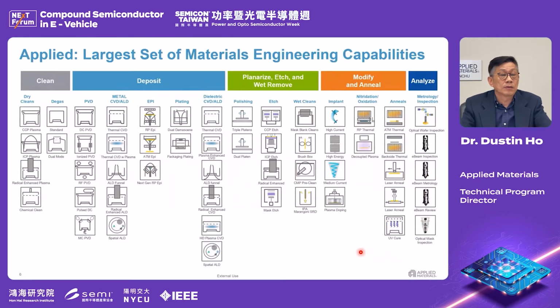Applied Materials offers a lot of equipment for our industry. To simplify, you can see you have clean, deposition, remove or etch, and modify and analyze. For deposition, you have dry cleaning, metallization PVD or metal CVD, and epitaxy, plating, CVD, ALD. For remove, you have CMP polishing, you can etch, or you have a wet clean. For modify, you have ion implanter, and then RTP for oxidation, nitridation, and annealing. For metrology, we have CD-SEM, E-beam metrology, etc.